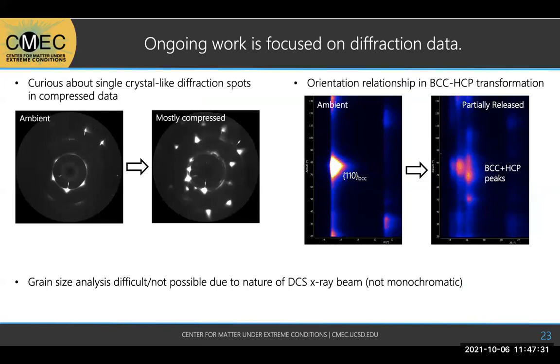So my ongoing work is obviously focused on my diffraction data. That one slide I had in this talk was obviously not enough. There's a couple things I'm interested in. First, and most importantly, is that we see single crystal-like diffraction spots in the compressed data. So, the ambient image on the left, and then we have something that we think is mostly compressed based on our initial analysis, but we see these bright spots, which are a single crystal diffraction pattern. A polycrystalline diffraction pattern would be more like just rings instead of spots. And so we were really confused by this.